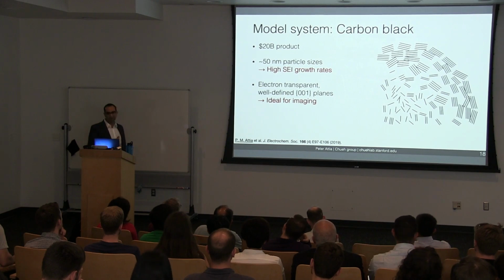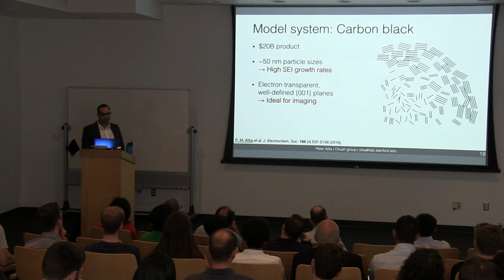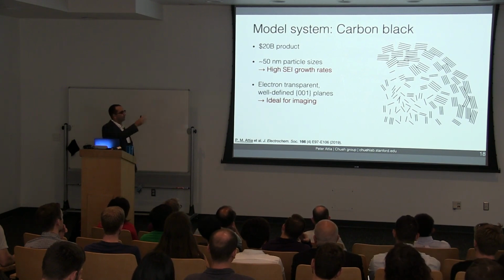The structure of carbon black looks something like this. We see that it has these small graphitic domains. But what's really great about it is that it has this well-defined interface, which makes it easy to see the boundary between the bulk material and the SEI itself.